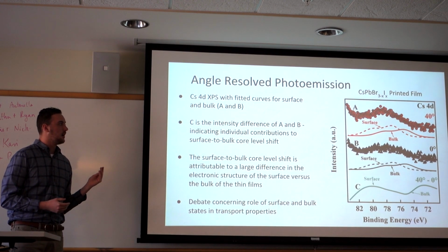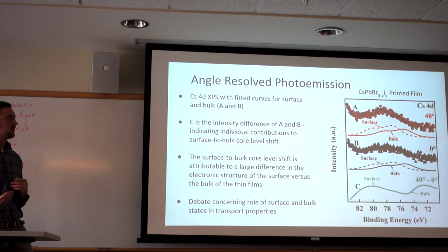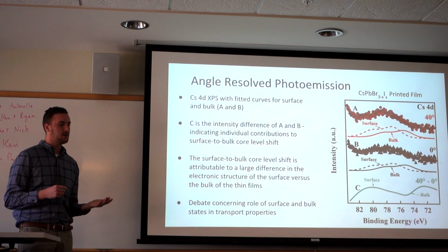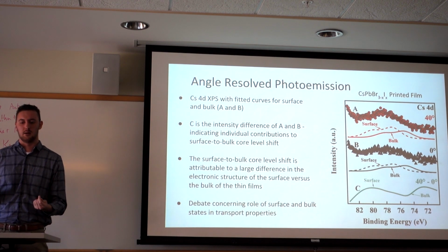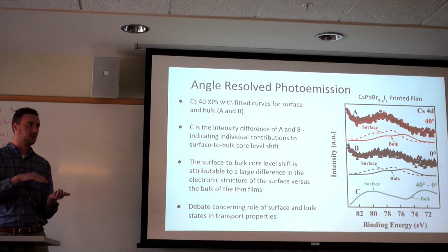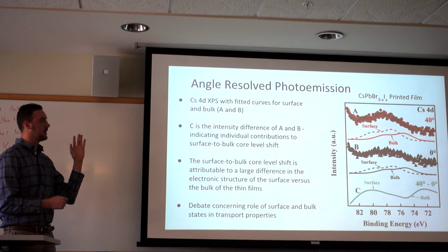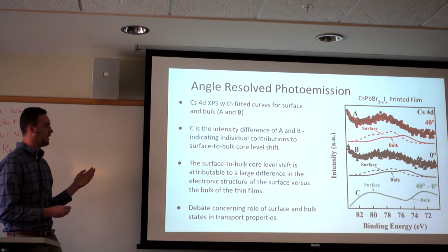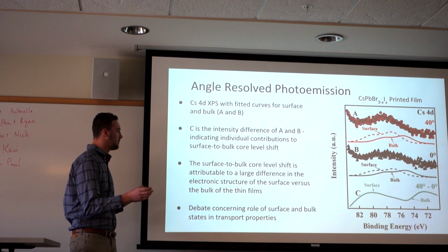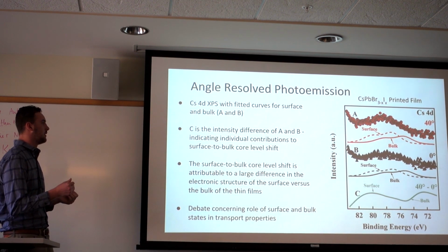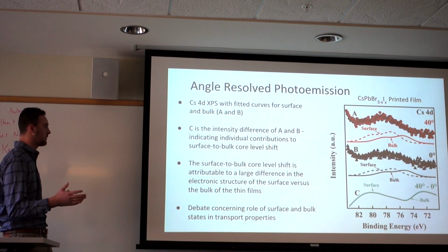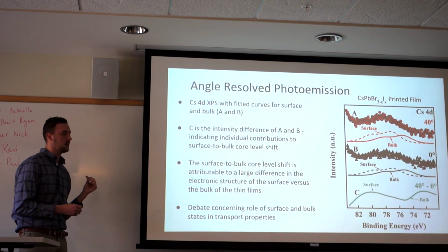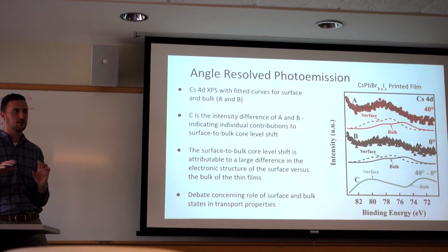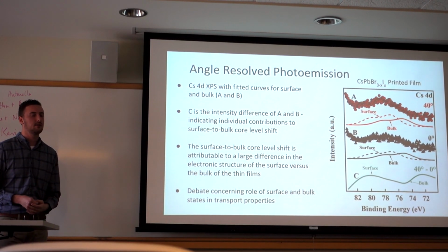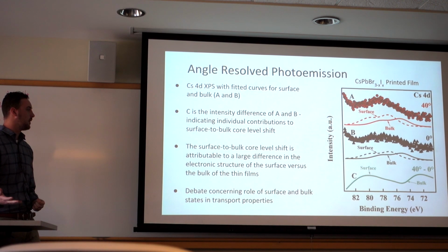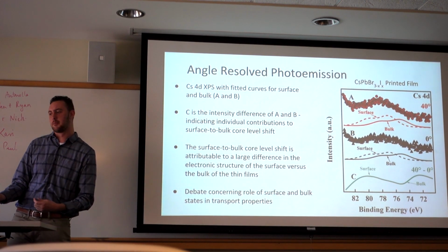The 0 degrees photoemission gives a greater contribution of the electronic properties from the bulk of the material, and then the 40 degree spectra gives a greater contribution from the surface because it skims the surface more. And then we take a difference of the two intensities just to separate the contributions a little bit. And we see that there's a large surface versus bulk core level shift, and we can attribute this to the difference in the electronic structure between the surface of the material and the bulk. But there's still a lot of debate going on about what relevance this has in the transport properties of the material.